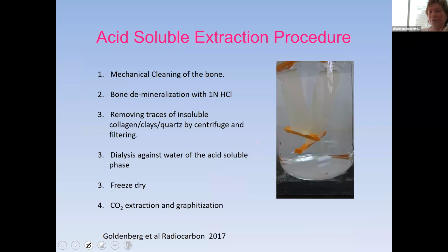So we took our bones and dissolved them, but instead of throwing away the soluble fraction, which is normally quite a lot, we put it in a dialysis bag and changed the pH in a controlled way, and we recover the collagen which has reassembled in our dialysis bag.